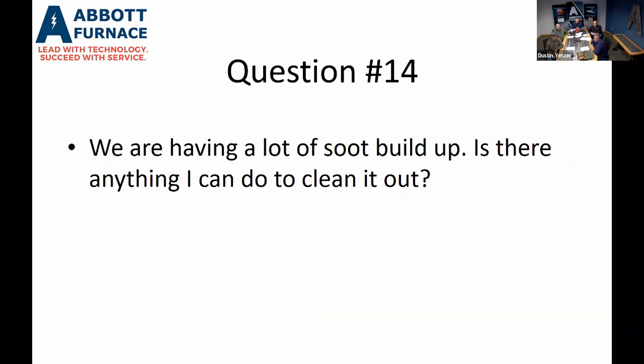We're having a lot of soot buildup. Is there anything I can do to clean it out? This question comes around quite often, especially with our powder metallurgy customers that tend to have some lubricant that has dissociated and turned to soot in the furnace. The belt tends to drag it out the back sometimes, but often it builds up along the edge of the belt. So sometimes when you're changing belts, you can scrape or brush some of that out of there.